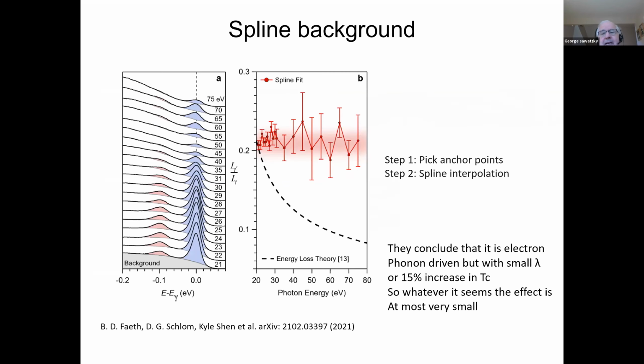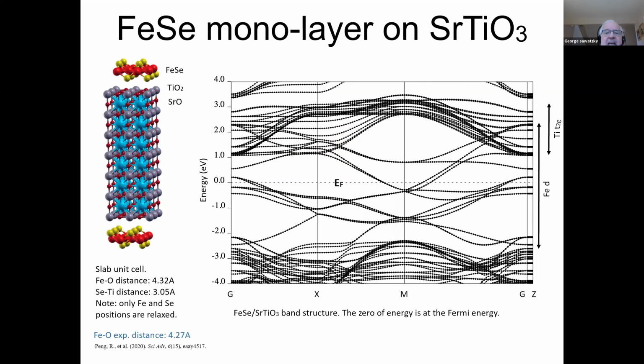So I say that, well, okay, I don't really want to worry about this terribly much anymore, simply because it seems to be such a small effect that, even if it was there, it couldn't really affect the superconducting transition temperature much. So we're left with the problem of why. What's that due to, this large increase in the superconducting transition temperature? And then we come into a very big problem.